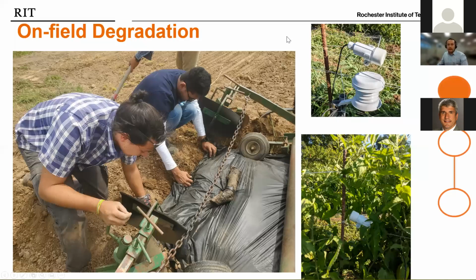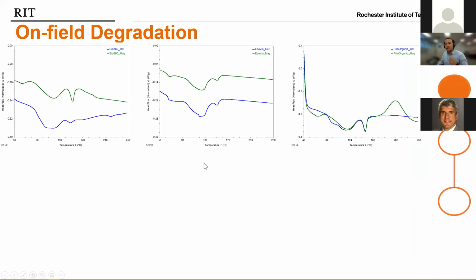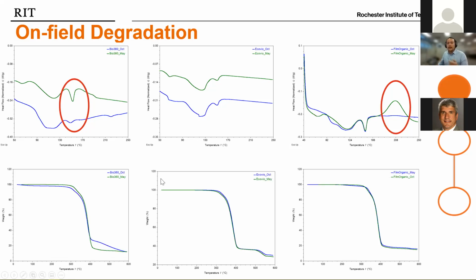But we not only did mechanical testing, we also did some thermal testing. The one I was talking about, the differential scanning calorimeter, allows us to have an insight on the plastic structure. Here we compared the May samples just after we laid them to the October samples, and we do see some clear differences in the behavior of the plastic. So DSC may be a good way to differentiate degraded versus non-degraded samples. Another thing we did was thermogravimetric analysis, which shows us how the weight of the material changes with ramping temperature and gives us an insight on the dynamics of the plastic. Sadly, we didn't see any major differences between samples of May and October, so it's not as sensitive to degradation as the DSC.